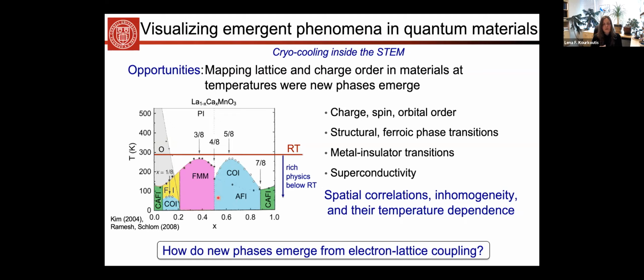But the advantage of STEM in particular is that we can probe the atomic scale structure and electronic structure. We can probe it within the material, not only on the surface. And we can map it both locally and over large length scales. And that lets us access the heterogeneity that I introduced to you in the beginning, which is to understand the role of defects, the role of spatial correlations in a quantum system. And often these correlation or competition between two phases gives rise to these new quantum phenomena, or why these materials act differently than others. So this is the motivation.